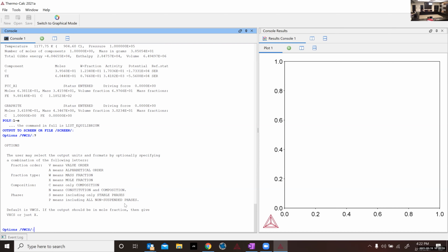Sometimes what we'll do is we will set a phase not suspended but dormant, which means that it's going to do all the calculations for it, but it's not going to consider it in equilibrium. And we can do that to calculate a driving force for precipitation. So say we have FCC and BCC and cementite, and we want to calculate the driving force for the precipitation of BCC from the FCC. Well, if we just calculate equilibrium, we're going to calculate an equilibrium with FCC plus BCC. But if we make the BCC phase dormant, it'll calculate the equilibrium without BCC, but it will give you the precipitate composition and the driving force for precipitation of that composition.